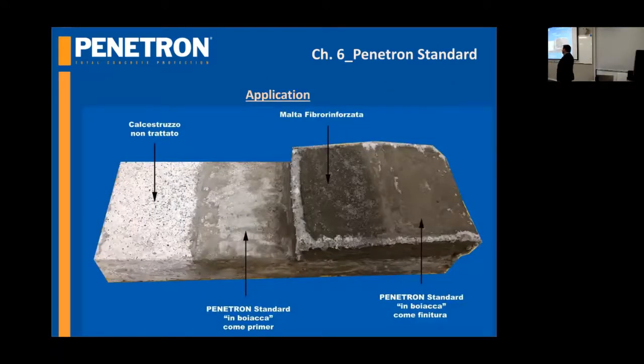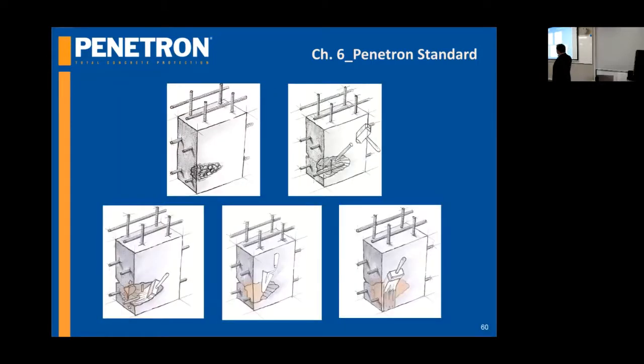Because of this, we use it as a primer. If I have to make a repair on concrete, we use it as a layer to make a bond between the concrete and the mortar I'm using on the concrete support. This is a typical application of a repair. Here is an imperfection, could be a crack, could be a little void. We have to remove it, clean it well, use Penetron Standard as a primer, then apply a mortar, and again Penetron Standard as a coating.